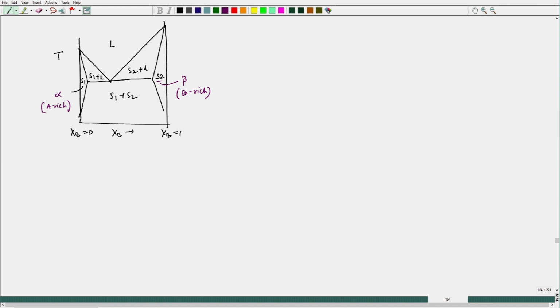Now, in this case we see that all those metastable compositions are entering like this. You recall we have done it like this for the metastable composition. Metastability is decided by a common tangent again, but that common tangent will be lying above the stable common tangent, or the stable equilibrium common tangent.